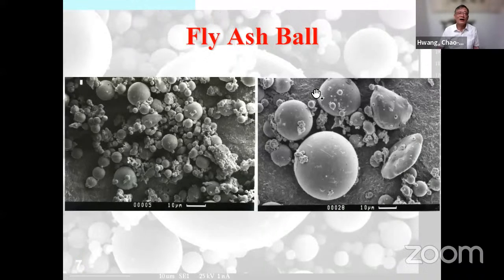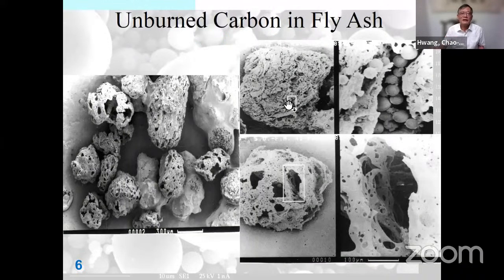There is also some unburned carbon, because if we do not grind the coal very fine, some particles will become unburned carbon in the fly ash. This unburned carbon can influence workability. So normally for the fly ash, we use a grinding method to grind the particles and release the small particles out. These small particles are very active, just like silica fume.